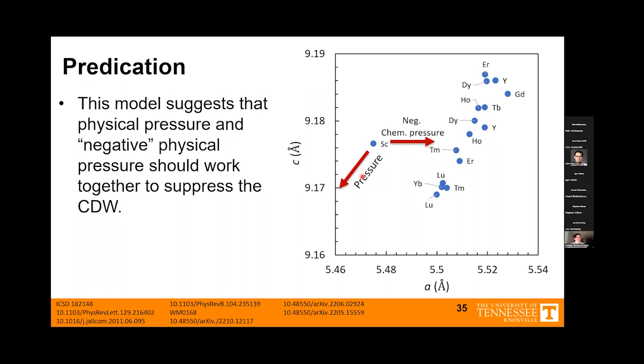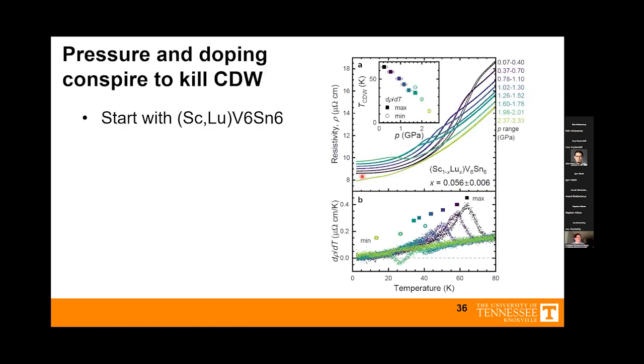These two should conspire. If we take a doped scandium vanadium tin sample where the charge density wave is suppressed, we expect that charge density wave to be further suppressed with pressure, not increase again as we shrink the lattice. And that's exactly what we see. So if I start with a lutetium doped scandium vanadium tin sample, where my charge density wave order is 60, 65 Kelvin, applying pressure